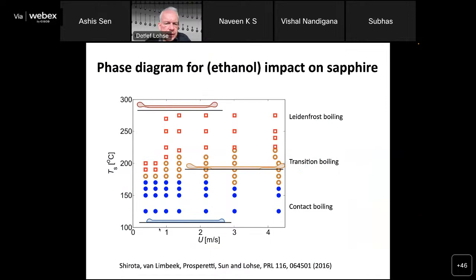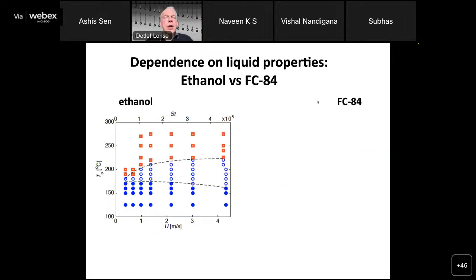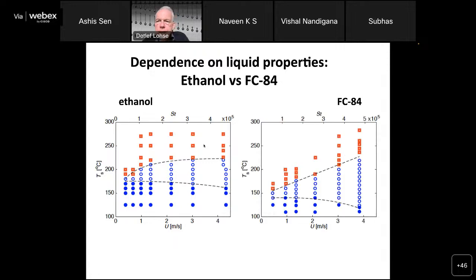So here's the phase space, impact velocity here, and temperature here, with this contact boiling regime right here, the transitional boiling regime here, and the Leidenfrost boiling regime up there. The question now is, how does it depend on the liquid properties? And here I show you this phase diagram for ethanol, which you saw before, and here I show it for FC84, one of these cooling liquids. And what you see is that it shifts down quite a bit. So the Leidenfrost state here is only achieved at much higher temperatures as compared to here.